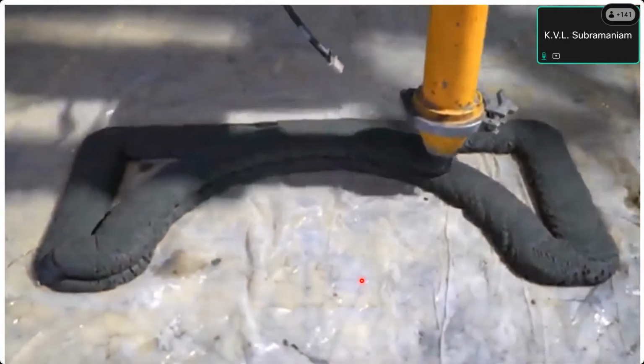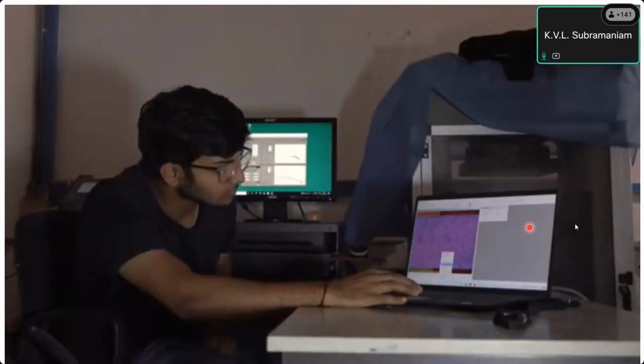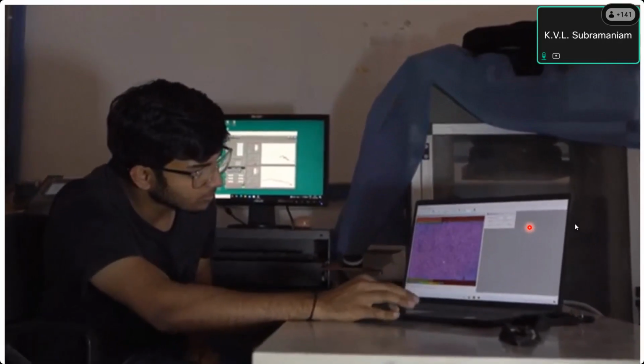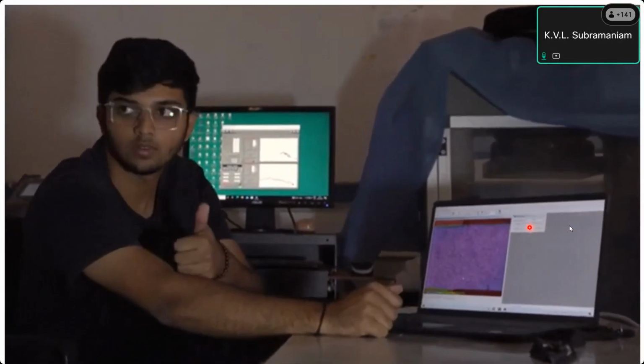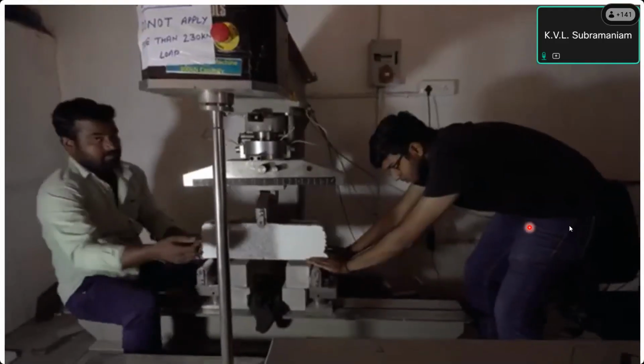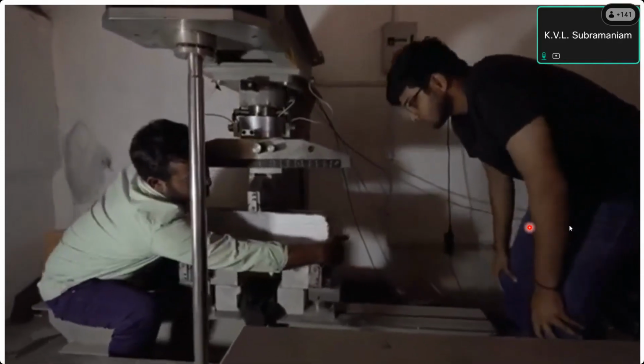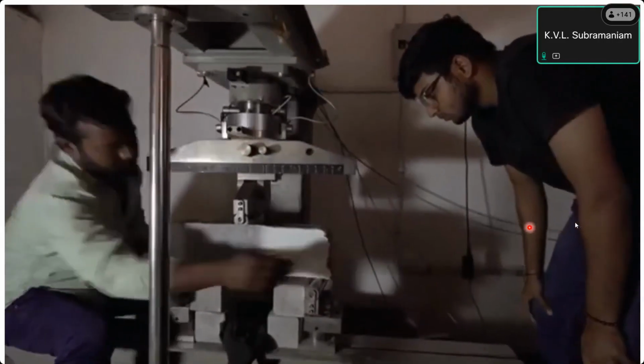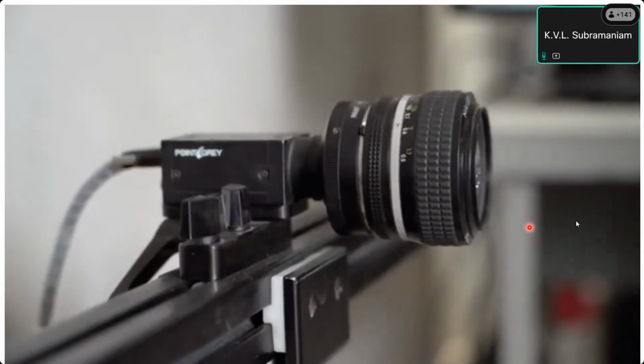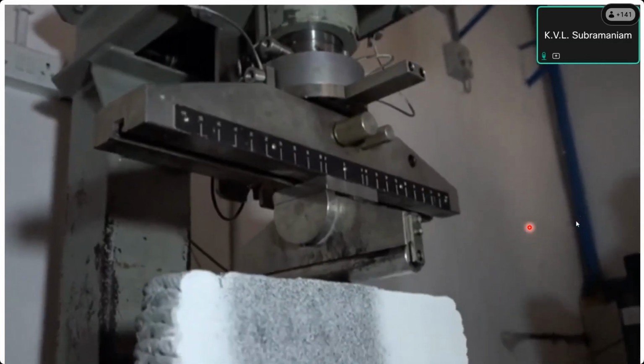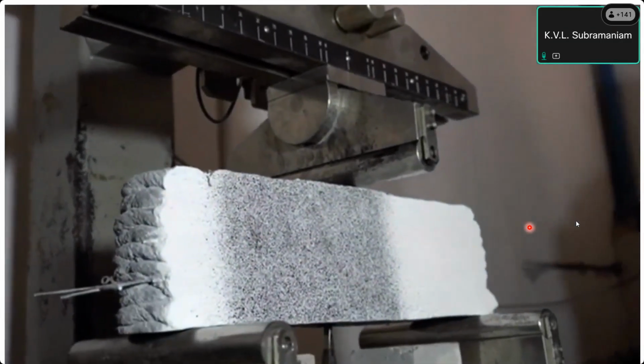We tested cubes that were cut from printed specimens to account for any directional variations that might not be properly reflected in mold casted cubes. We tested them for compression and use those results to finally obtain the compressive strength of the mix. Next, we tested a few beams to identify and understand the behavior of the beams in flexure. We did the DIC analysis of the same to understand how it is behaving under fracture.